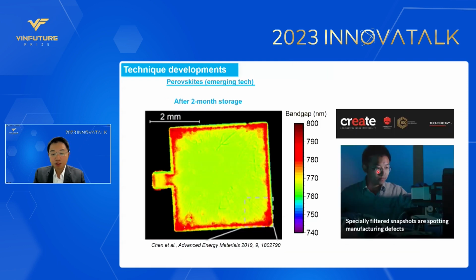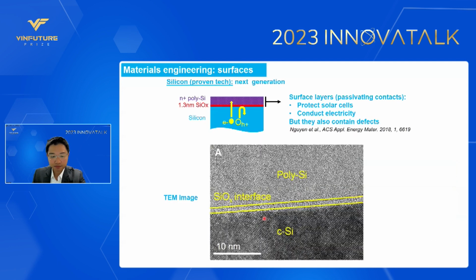Another example is for perovskite solar cells, an emerging technology. This is a solar cell that we stored in a nitrogen cabinet for 2 months. With our technique, we can detect the degradation around the edge using our imaging method. You can see the band gap of the material has changed around the edge because the air slowly invades the solar cell around the edge. When we put this cell in the air, the degradation happens much, much faster. And with our technique, we can visualize that. Those are the measurement techniques.